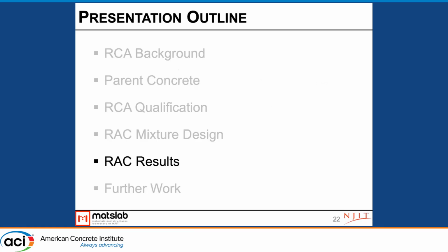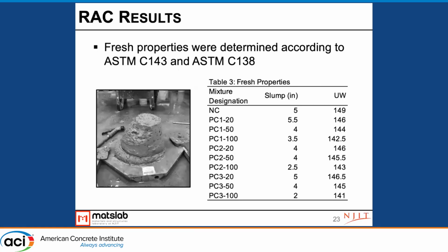Now I'm just going to go through some of the results. These are the fresh properties that we determined according to ASTM C143 and ASTM C138. So we have the slump and the unit weight. And again, as I said, if we're looking at the natural system with no RCA added to it, that's just a natural aggregate system. Our unit weight is around 149. As you can see, none of the other systems have a unit weight that is that high. They all decrease. They decrease pretty consistently as you increase the RCA content. So for any 20% mixture, it's around 146 and so on.